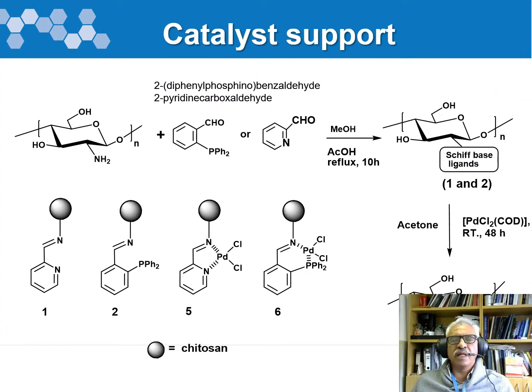And of course, with chitosan, you can do a Schiff base link of the ligand. And then once you've got the ligand, you can put the complex on there. And of course, once you've complexed, you use this as your catalyst, and you can try and repeat that cycle. We found that for up to 4 or 5 times, we still didn't lose a lot of it.